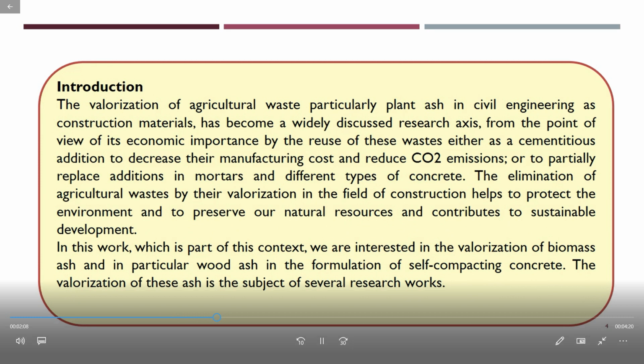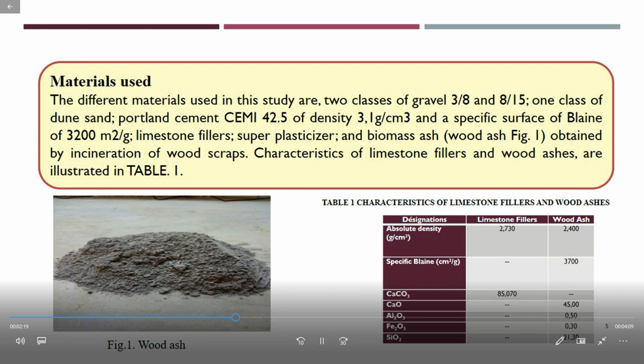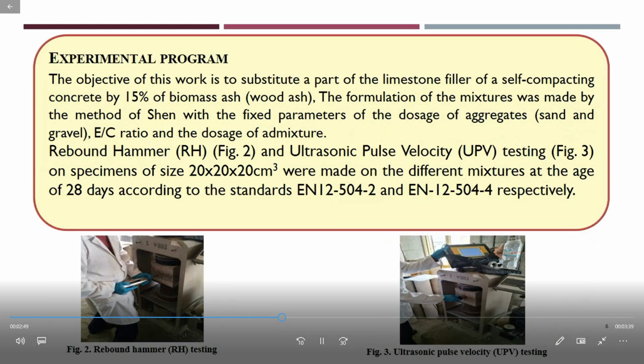In the valorization of biomass ash, and in particular wood ash in self-compacting concrete, the valorization of this ash is the object of several research works. The materials used are different: two classes of gravel, 3/8 and 8/15, one class of dune sand, Portland cement, limestone filler, superplasticizer, and biomass ash. You can see in the table the oxide constituents of the wood ash and the limestone filler.